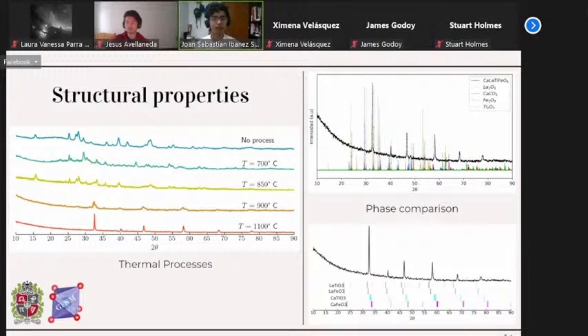In particular, you can see that first the calcination caused some peaks to decrease in intensity, while in the first sintering, the main peak, the most intense one found at about 32 degrees, began to form more explicitly. By sintering at 900 degrees, most of the strange peaks disappeared, although the majority phase was not yet present. And with the last sintering at 1100 degrees Celsius, we found some well-defined and intense peaks.